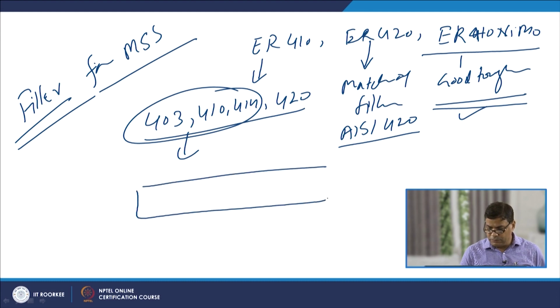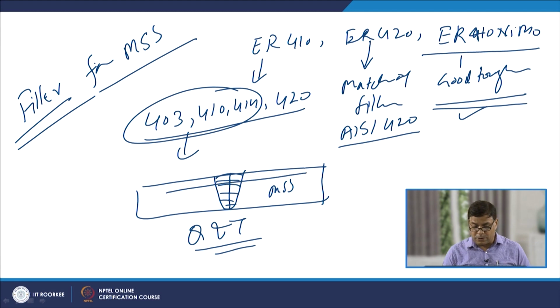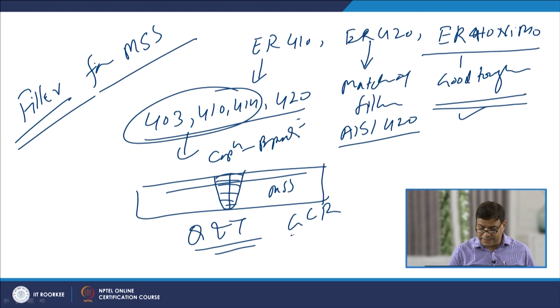While in the case of AISI 420 martensitic stainless steel, when it is welded with the matching filler, the entire weld as well as base metal will be the same, and in that case we can apply the complete QT heat treatment for having uniformity in properties across the weld joint. So the 420 filler for joining the AISI 420 base metal will lead to uniformity with regard to composition and properties, and therefore whenever we need very good corrosion resistance, uniformity in mechanical properties and good response to heat treatment, the matching filler actually helps in realizing this.